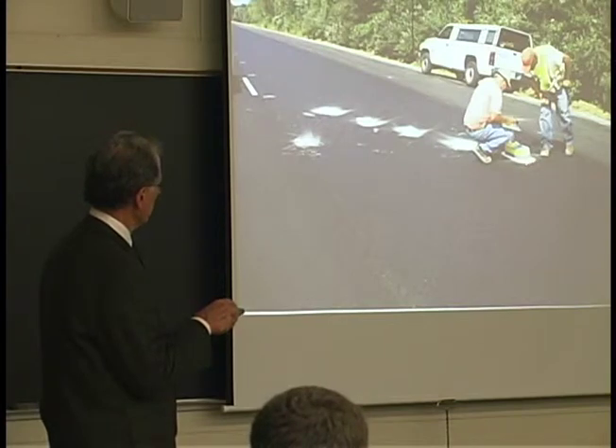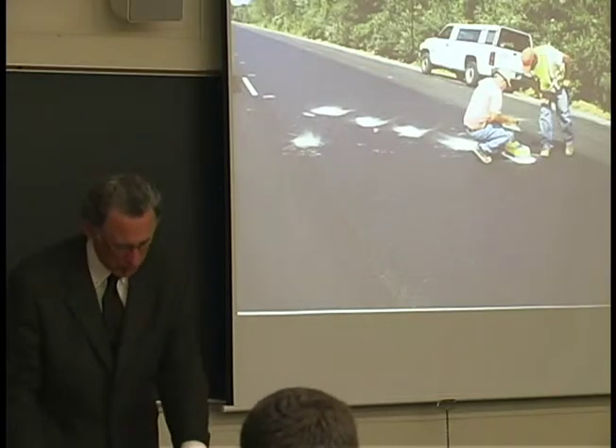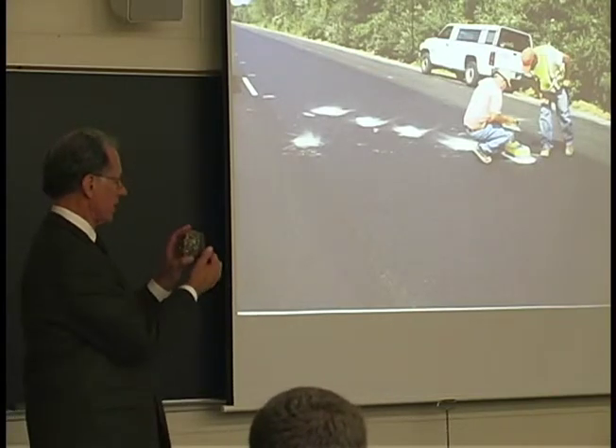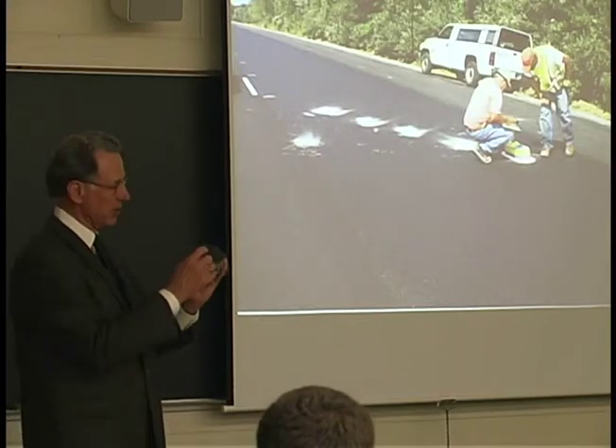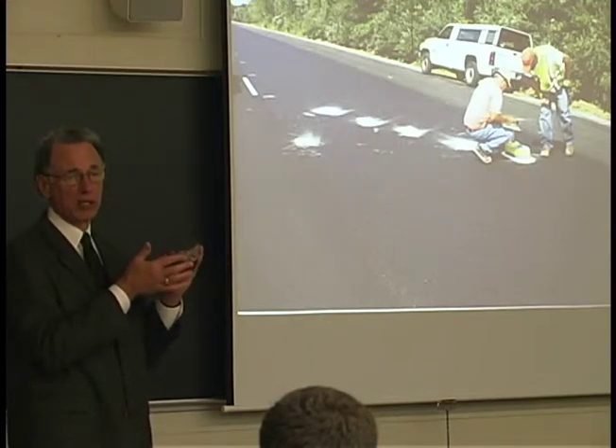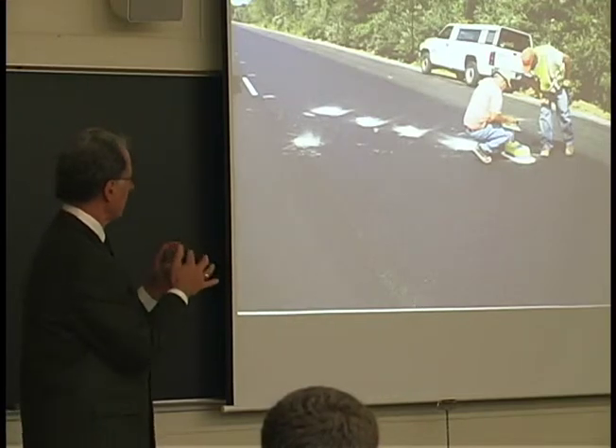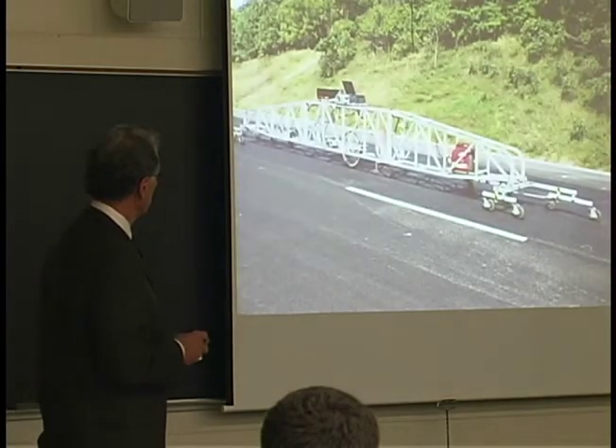We found over the years that a lot of times the porousness of the very, very top surface, in other words, this porousness right there, will affect the reading. So what you want to do is just fill those, because this porousness here has nothing to do with the consolidation down here. So we'll fill that with some of that white powder, mineral filler, in order to do that.